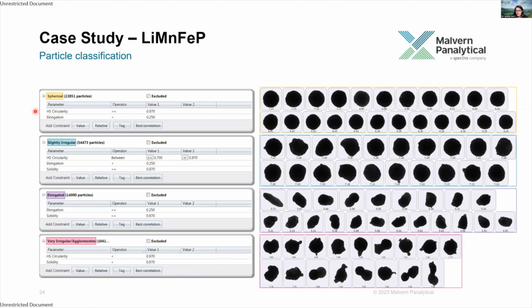So you can see, for example, for the spherical, to be classed as spherical, the particle would have to have a very high sensitivity circularity and an elongation below 0.25. And on the right, you can see some example particle images for the particles that fell into each class.